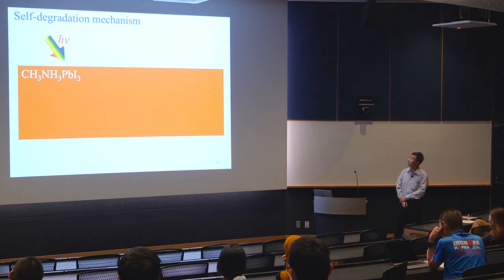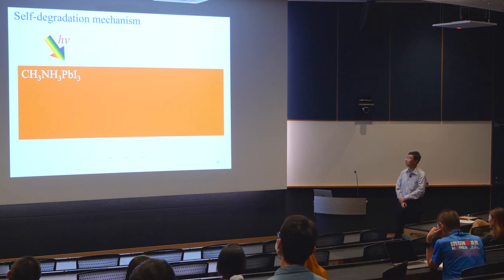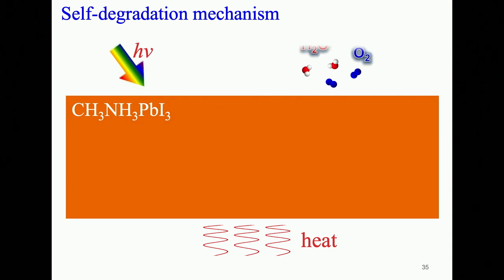In solar cell operation, light is incident on the solar cell, and part of the light will be converted into electricity, but a larger portion of the remaining light will turn into heat, which leads to an increase of the cell temperature and causes the initial degradation of the perovskite layer on a local scale. Also, the perovskite solar cell is operated in ambient conditions, so ambient gas molecules such as water and oxygen can interact with the perovskite layer, also causing the initial degradation of perovskite. And a byproduct of the initial degradation is iodine-2.